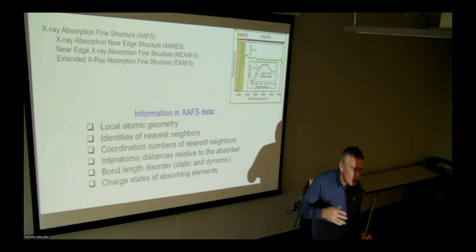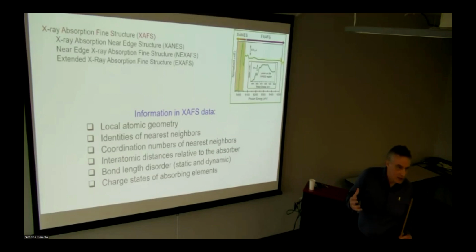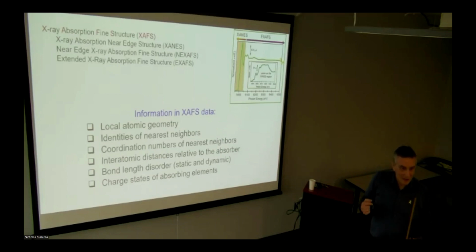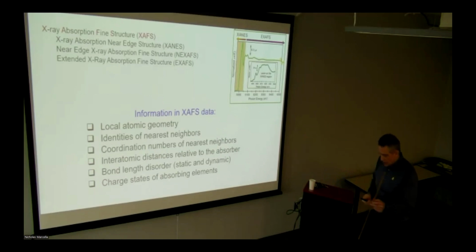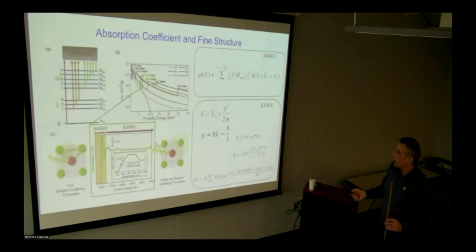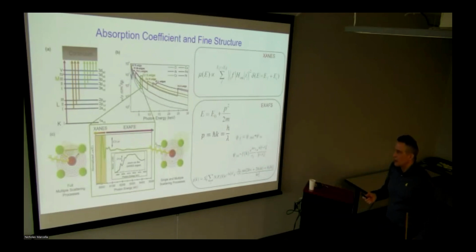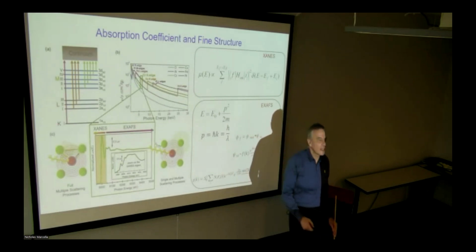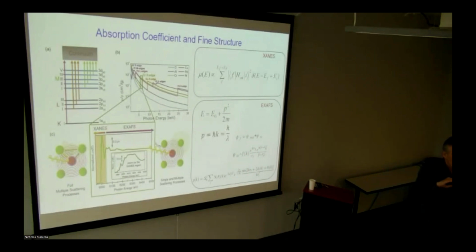In quantum mechanics, it's nothing like what I just said about the fixed wall, but the type of elements that we're scattering from affects the phase of the scatterer. And that can be used as a marker. The phase of scattering, which goes into the equation, delta, is a marker of the neighboring element, and also what is called scattering amplitude, which is like a cross-section of scattering. For different wave numbers, different elements have different cross-sections of scattering.